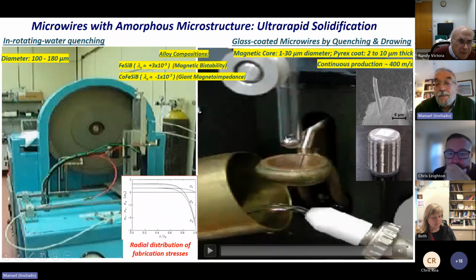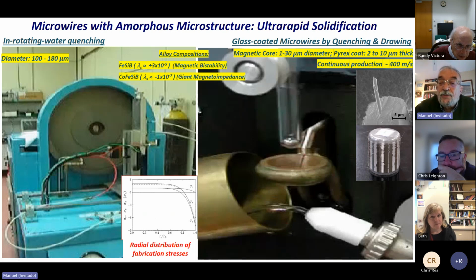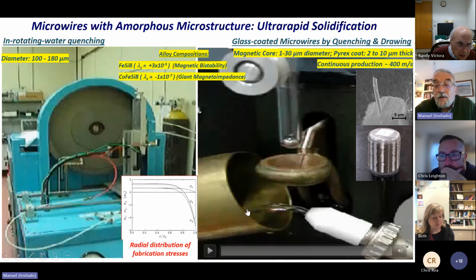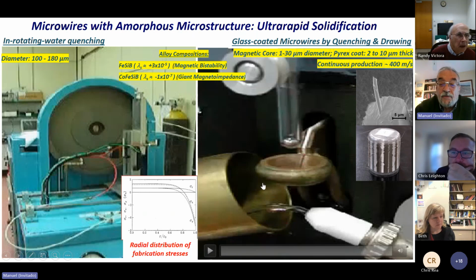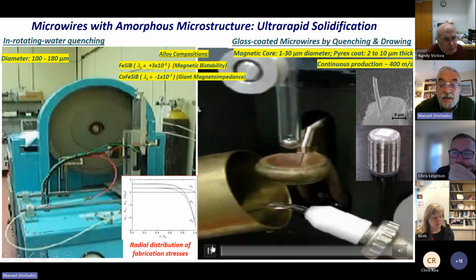So here you see, well, I will explain a little bit. We have a Pyrex tube here, and this is a metallic polycrystalline pellet of the composition we want to prepare the microwire. This is an induction coil to heat the polycrystalline metallic pellet up to 1,200 degrees centigrade. And there is a water jet to increase the quenching rate from 1200 degrees centigrade to room temperature in around 1 millisecond. So the velocity of quenching is about 1 million degrees per second.